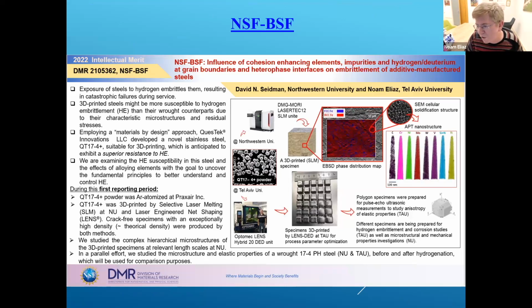With Professor David Seidman at Northwestern University, I have an ongoing NSF-BSF project on the susceptibility to hydrogen of a special equivalent to 17-4 PH stainless steel that was developed by QuesTek, a company of Greg Olson that you know from MIT and Northwestern and so on. They developed the equivalent, they call it 17-4 plus, that is supposed to have better mechanical properties than the wrought 17-4. They developed it for powder-based fusion. I asked the company that synthesizes the powder to synthesize, especially for us, for DED, larger powder. And we are studying the susceptibility of these materials to hydrogen as compared to the wrought alloy.